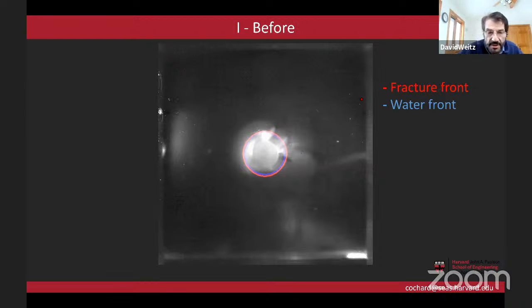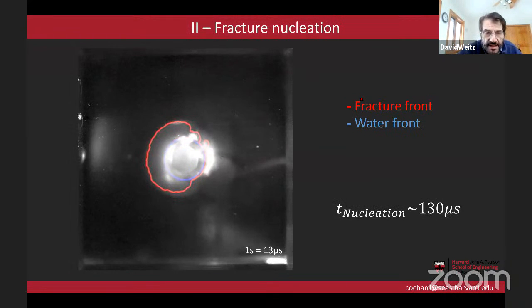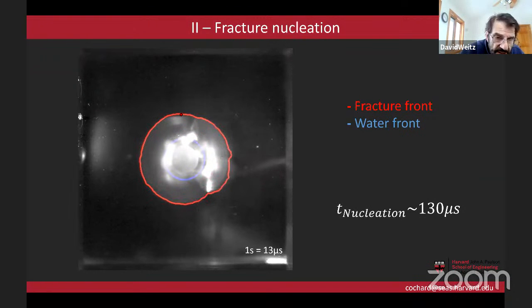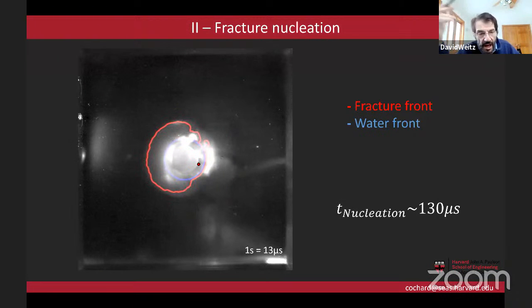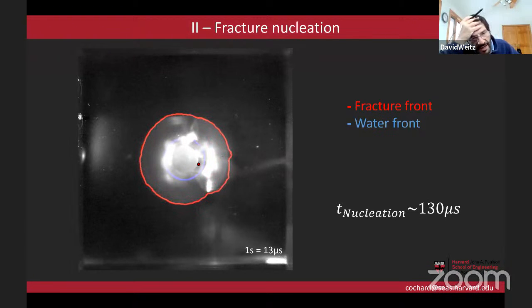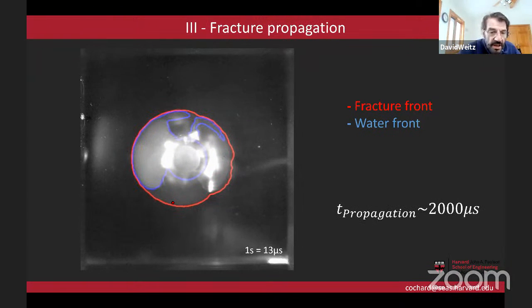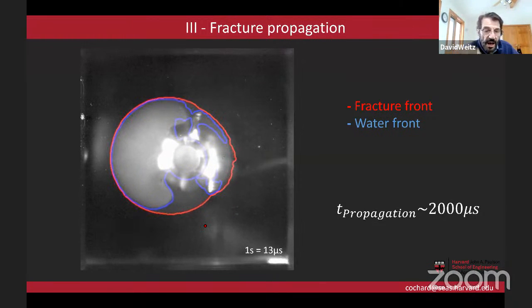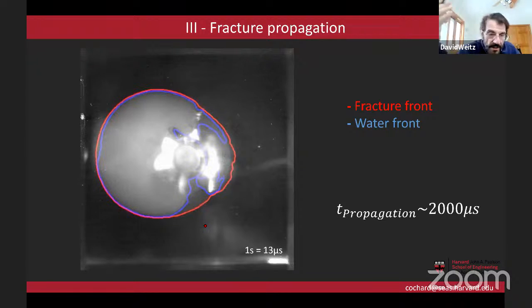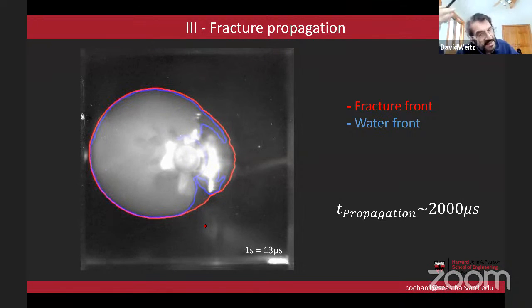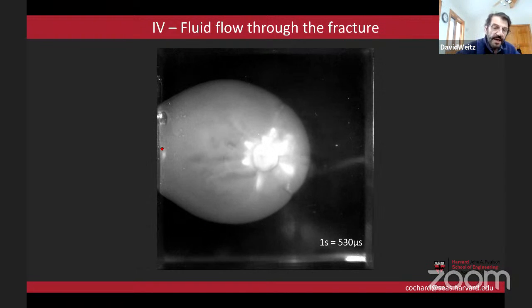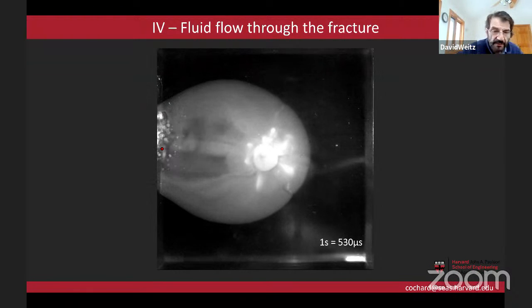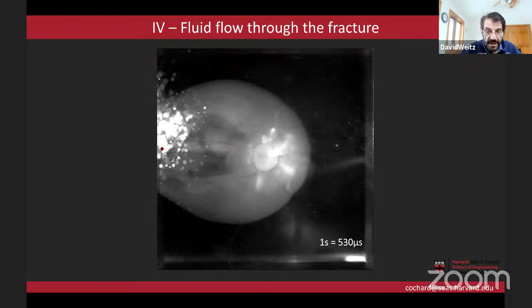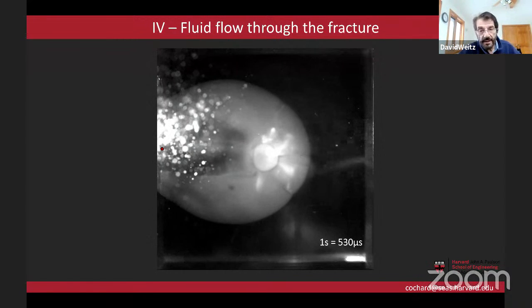So now we can look at this in more detail, and we can watch this. This is the nucleation. So you can see at this point, the fluid is way behind the crack. It nucleates, and you see the crack is out, the fracture is way out in front. The next stage, the fluid catches up, but the crack is always in front of the fluid, and then finally you get a break, and the water, the hydraulic fluid, goes out of the sample. You get a fracture, the whole sample is torn apart.